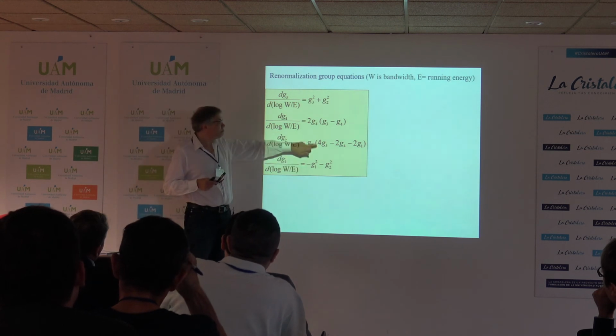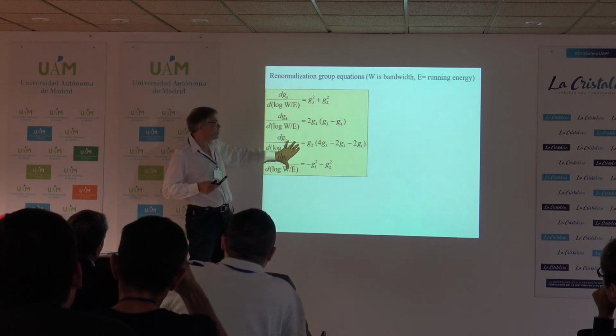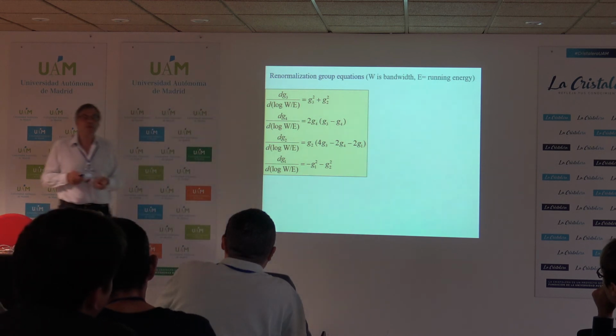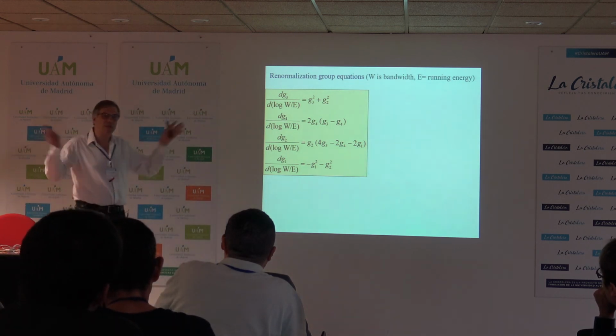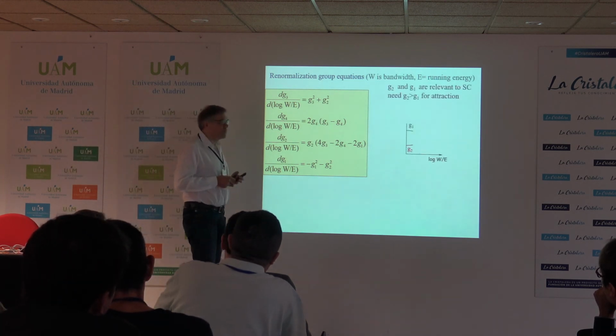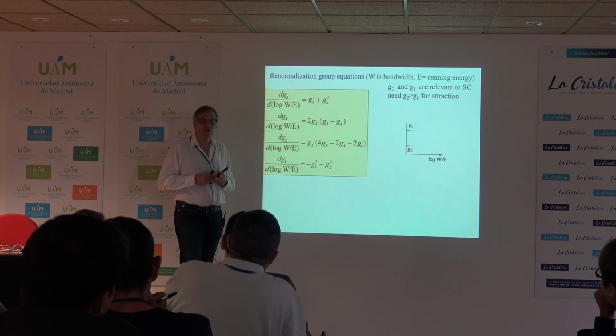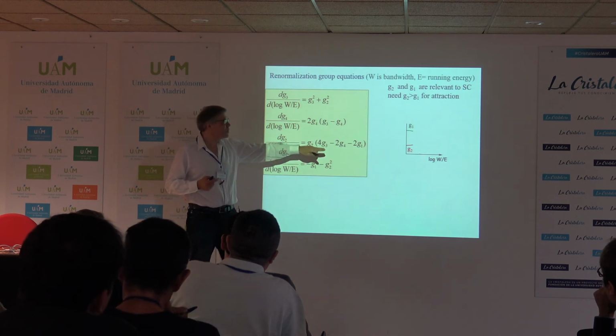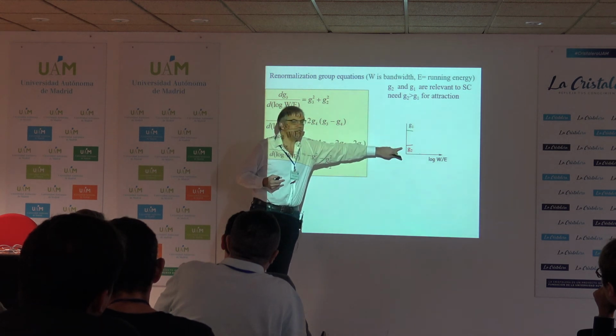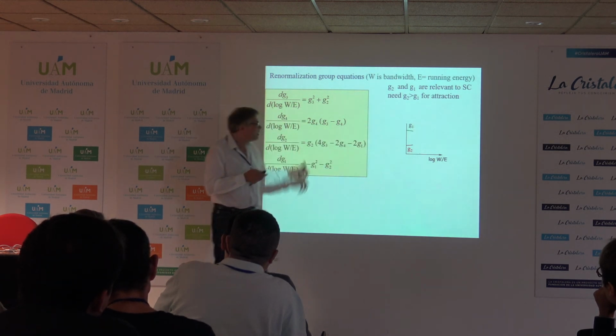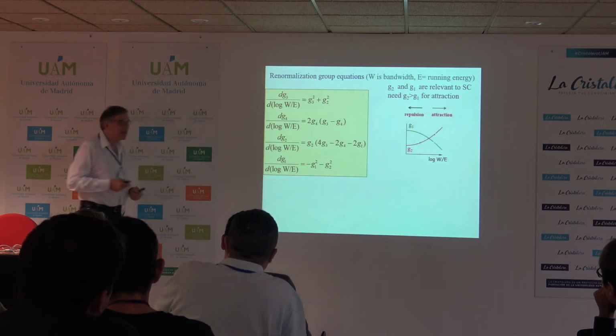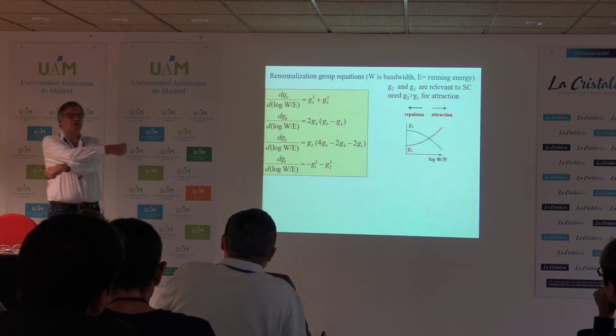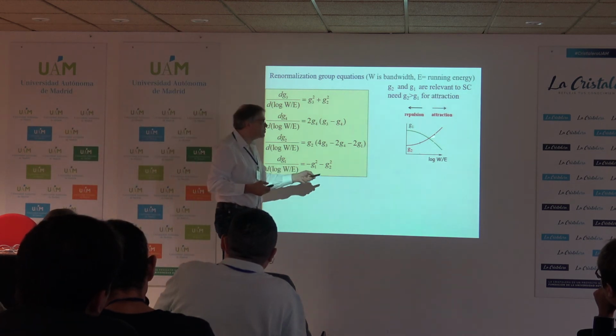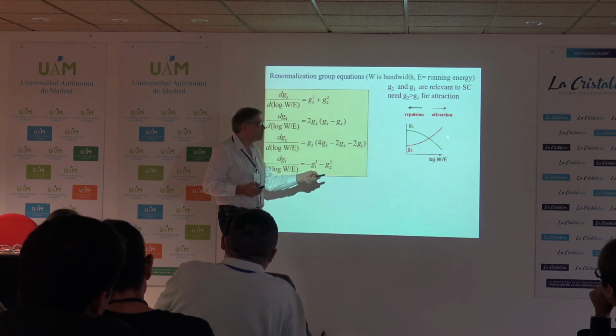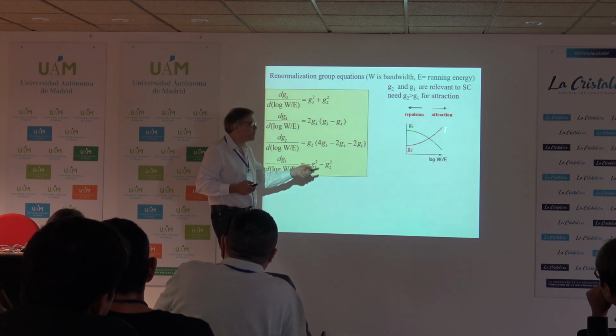But there is a coupling between these two parts and these two parts. And if I solve these equations, and in fact, if you plot them in Mathematica it will give you the answer in a second, what you find is this. The system self-generates attraction, meaning I start the process with repulsive G1 larger than G2. So this is repulsive interaction. I run these equations, and what I get is that one interaction goes down, another interaction goes up. It's interesting. The system self-generates a scale below which, meaning larger values of this logarithm, smaller is energy, larger is logarithm, the interaction becomes attractive.